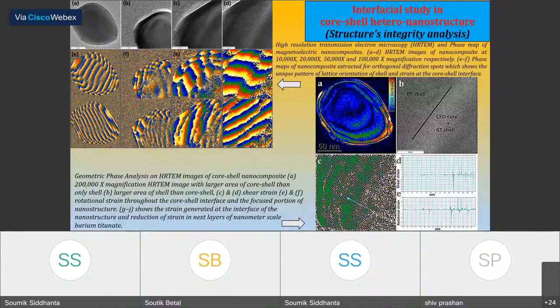Now, the question is whether this structure is really stable or not. To see this, we performed the GPA analysis, where we can see the stress being confined at the interface of these two layers. And high resolution microscopy, along with GPA analysis, shows us the strain is all confined at the interface of the layer rather than at the surface. This rotational strain, which can be seen in figure A here, is all confined at the interface, which further increases the integrity of the structure.